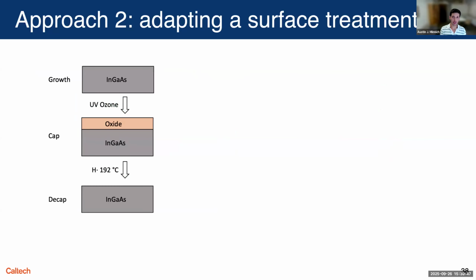We decided to try another strategy. And that strategy is based on noting a common surface treatment used in MOCVD and MBE fields. In that situation, often you create or you grow a semiconductor, and you might cap it by making an oxide, or just in air it grows an oxide. And then when you want to grow on it, you need to somehow get rid of the oxide. And the way that folks figured out how to do that is using atomic hydrogen at around 200 C.